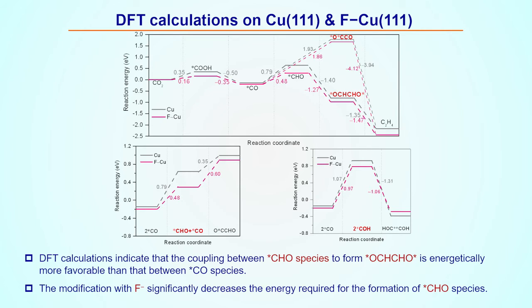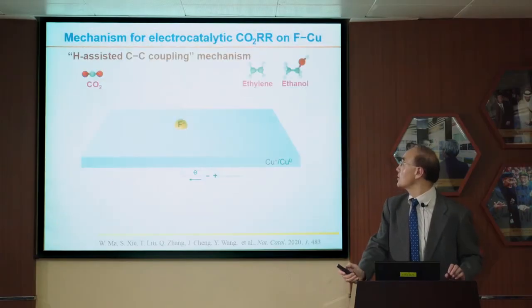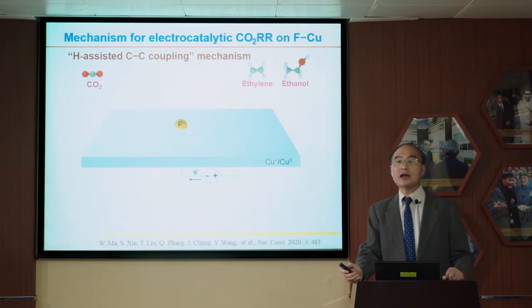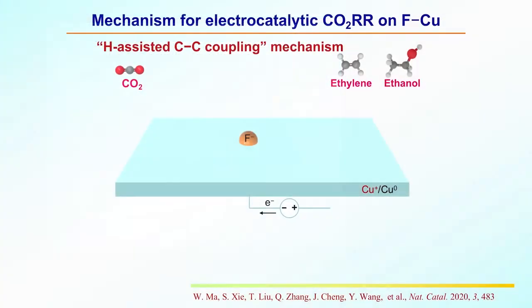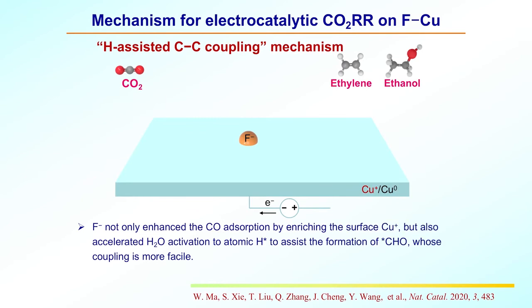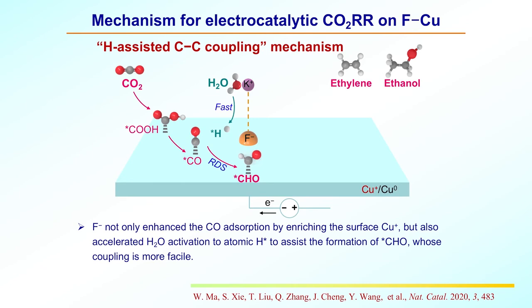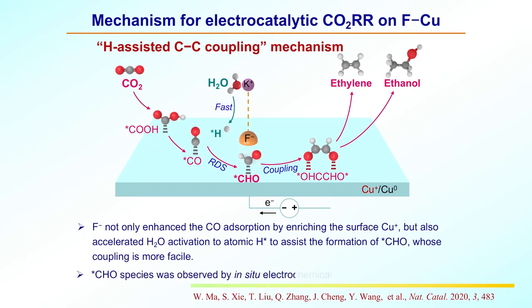So by combining the theoretical and experimental studies, we propose a hydrogen-assisted CC coupling mechanism. We found that fluoride not only enhanced the CO adsorption by enriching the surface copper plus sites, but also accelerated water activation to atomic hydrogen to assist the formation of CHO species, whose coupling is more favorable. This CHO species was observed by in situ electrochemical infrared spectroscopic measurements.